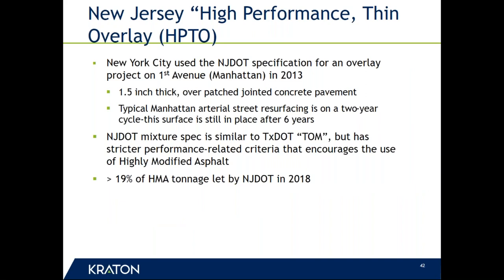What they did on that is they borrowed the New Jersey performance thin overlay specification, which is very similar in concept to the TxDOT TOM mixtures, or thin overlay mixtures. But what they have on this are very, very strict performance related criteria. It's really probably the first broad application of a balanced mix design concept in the United States. And when I say broad application, last year, over 19% of the mixture tonnage that New Jersey DOT let incorporated this type of mixture, which was the most of any mixture specification that they had.